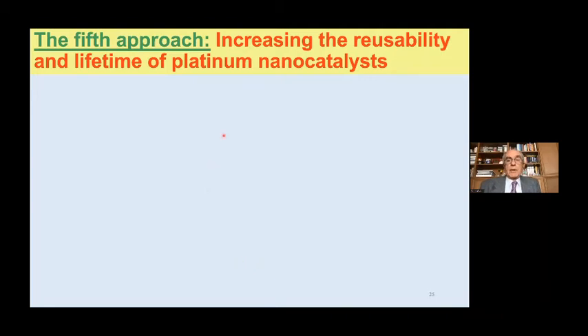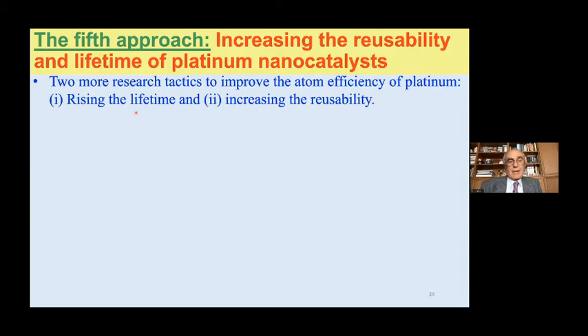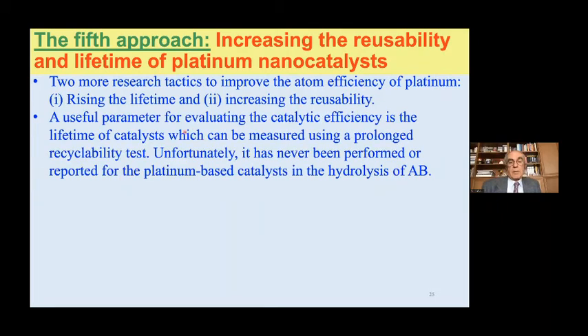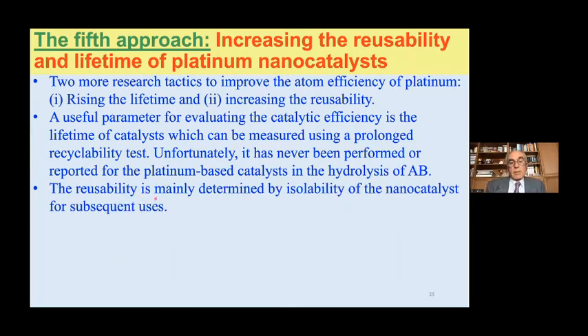The fifth approach is increasing the reusability and lifetime of platinum catalysts. So there are two parameters which can be used to increase the catalytic efficiency: rising the lifetime and increasing the reusability of the catalyst. Lifetime is a useful parameter for evaluating the catalytic efficiency, which can be measured by using a prolonged recyclability test. Unfortunately, it has never been performed or reported for the platinum-based catalyst in hydrolysis of ammonia borane. The reusability is mainly determined by the isolability or separability of the nanocatalysts for subsequent uses.